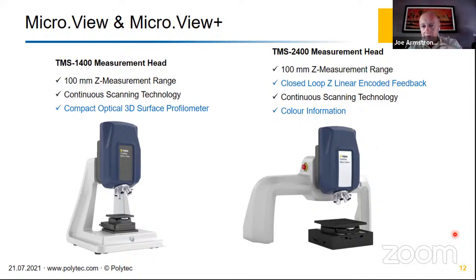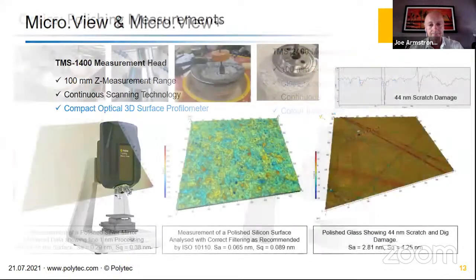If you are using the upgraded MicroView Plus, as we call it, again, you have the 100 millimeter closed loop scanning where you can get the high Z sampling over the large ranges, but you have two additional items. First, you've got the closed loop feedback. So your XYZ coordinate system has a reduced measurement uncertainty, but we also have available within the system the option for color information, which can be very useful for looking at wear mechanisms, looking at tribology features, maybe looking at different material types and giving you an indication of where one material starts and the other ends.